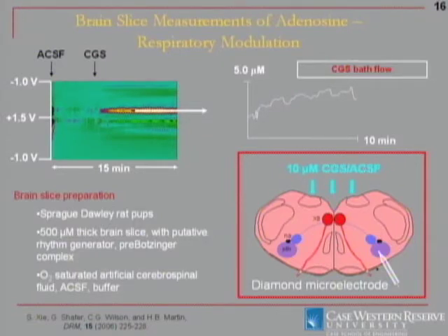And again, here's one of those false color plots where we've injected this molecule called CGS, there was a number after it I left off, so I apologize for not being complete there. But when we inject this, it's an agonist. It should enhance the release of adenosine in the tissue. And we do see a color change in the appropriate spot. You just have to believe me that that's where adenosine oxidizes. And we see the concentration, this is background subtracted, we see the concentration go up.